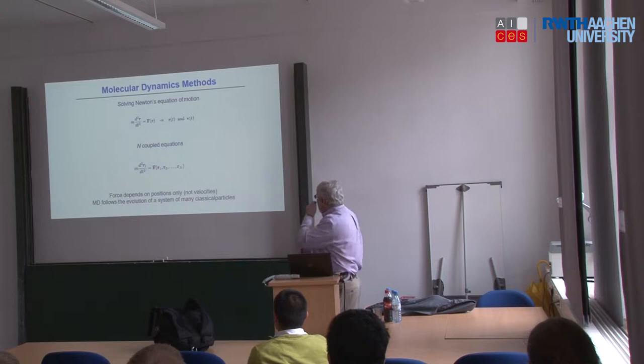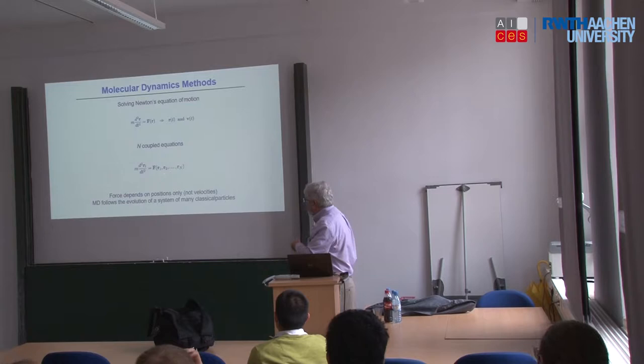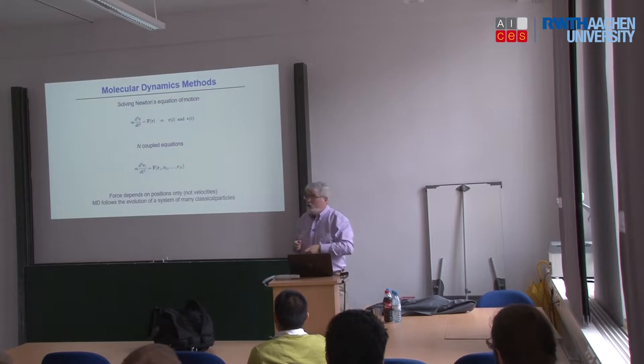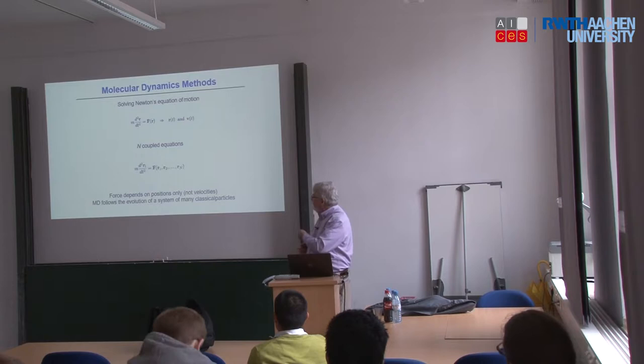Now, there's two parts to this. One is purely mathematical, which is just solving a simple differential equation, and we'll talk about that. First, get that out of the way. All the physics is lying in what this force is. What is that force? That is a description of the interaction between the atoms in the system. That's the potential. That's where all the physics gets added, and that's where all of the hard work is, essentially. Once you have that written down, then everything else is essentially automatic.